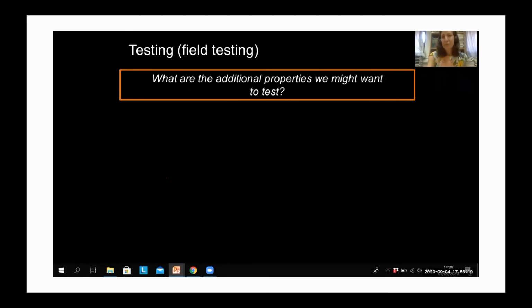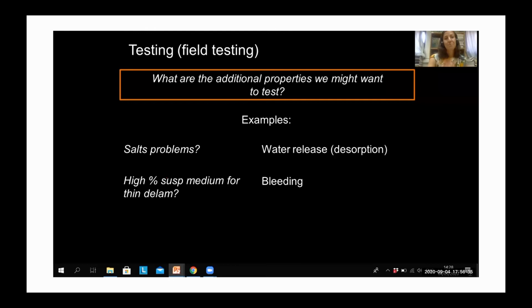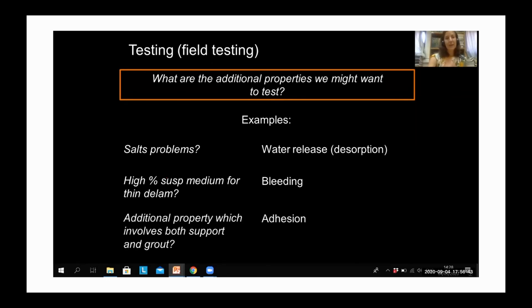And what other properties might we want to test? Of course, that depends on our specific problem, but these are a few examples. For example, if there are salt problems, we might want to test water release, so desorption of the grout. If it's a grout with a lot of suspension medium, because we want something very fluid, we might want to test bleeding. And of course, adhesion is quite important to test. Usually it's more useful to test simpler properties at the beginning, and then go to adhesion, which is more complex to test.